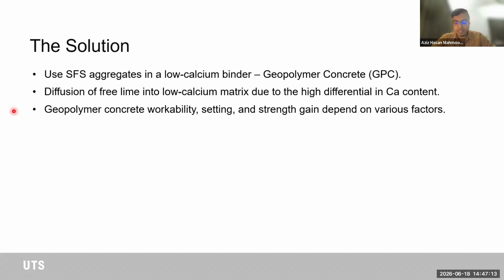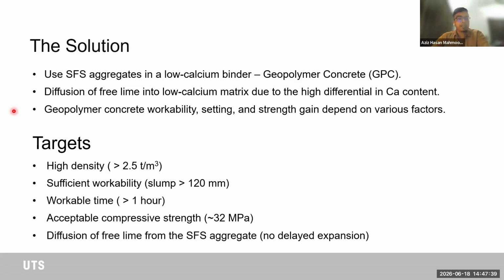And because this is site application and not within a laboratory environment where we can control the environment, on site, there's no way to control your environment, and the strength gain was a critical factor in designing the concrete mix. So we were trying to achieve sufficient strength in ambient curing conditions, and we were targeting some markers for the quality of concrete.